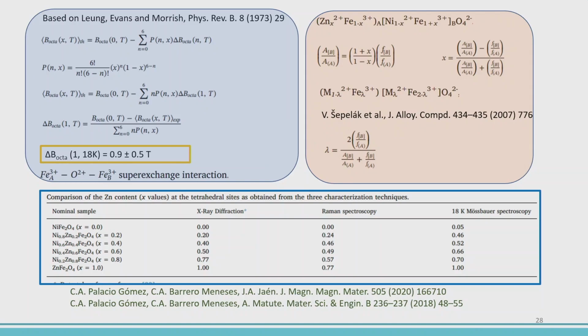You are right. When we started to study this, these are the results that we got, and we found that we have to be very careful with the way we determine these parameters in each method. There is a large overlapping of the lines in all techniques. You mentioned that it is better to have separated, isolated lines, but in all these techniques there is a high overlapping of the lines. This is one. The way we start the calculation is also important. We have a lot of assumptions. In each one of the techniques we make assumptions, and every time we make an assumption, we affect the results, because it is what we guess.